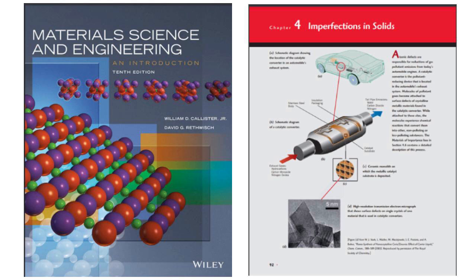Valence electrons, those are the ones in the outermost shell of an atom, right? Yeah. They determine how it bonds with other atoms. Exactly. And those tiny particles have a huge impact on whether two elements will work well together or not. For example, copper and nickel have similar atomic sizes, crystal structures, and valence electron configurations. So they form what's called a substitutional solid solution. They can basically swap places in the crystal lattice without causing too much disruption.